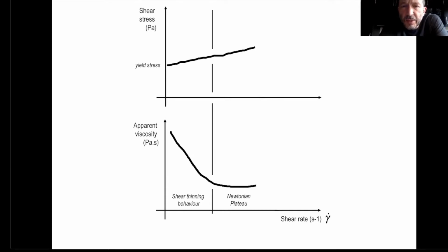The main feature that we will spend some time on today is the fact that this material displays a yield stress. It means that you need to apply to this material a critical stress, a threshold, for the material to flow. Above this yield stress, the material flows and its viscosity decreases with the shear rate, and this is called shear thinning. If you go to higher shear rates, you can even reach a Newtonian plateau where the material looks like a Newtonian fluid, but this often corresponds to shear rates that are not of interest for industrial practice. So we are mostly facing a yield stress material with a shear thinning behavior above the yield stress.